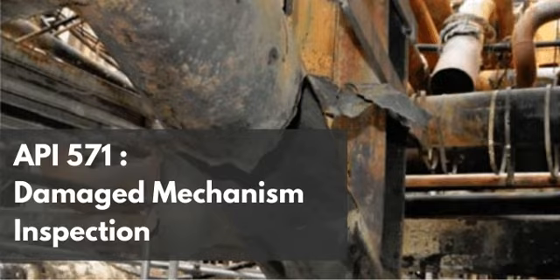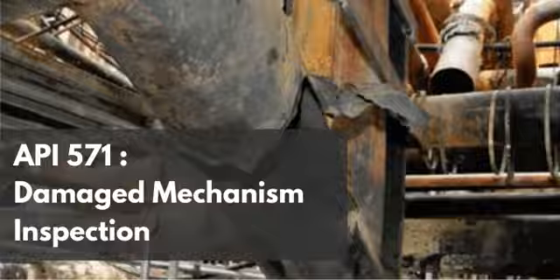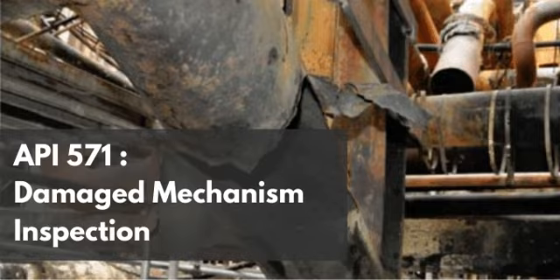Let us really drill down into that second condition, the temperature threshold, because this is the absolute golden rule for anyone monitoring operating windows or furnace temperatures. The metallurgical data explicitly provides the exact temperature threshold. What is the magic number? The process typically requires metal temperatures above 1,100 degrees Fahrenheit. That is 595 degrees Celsius.